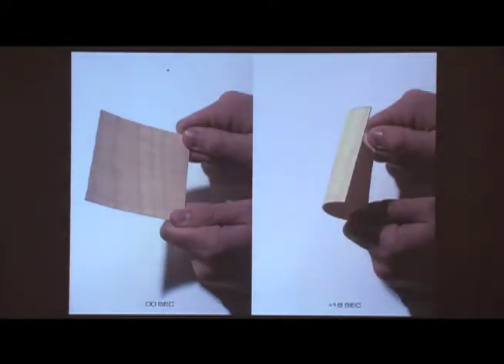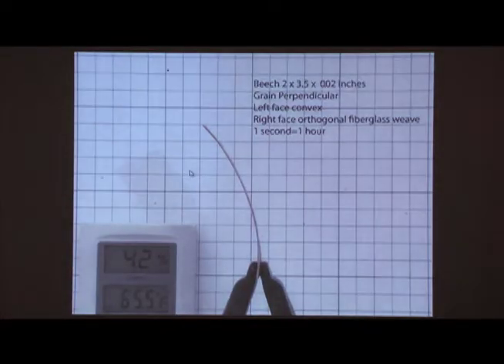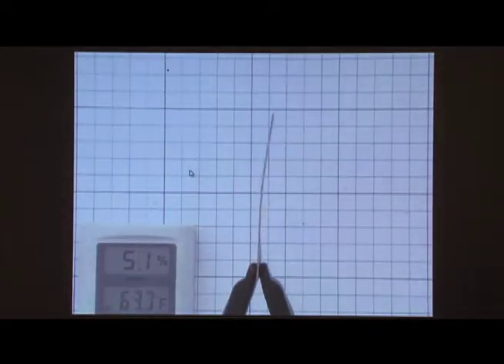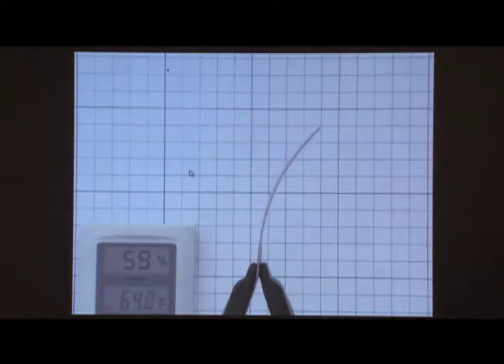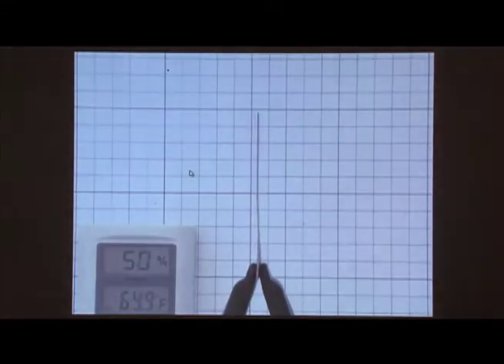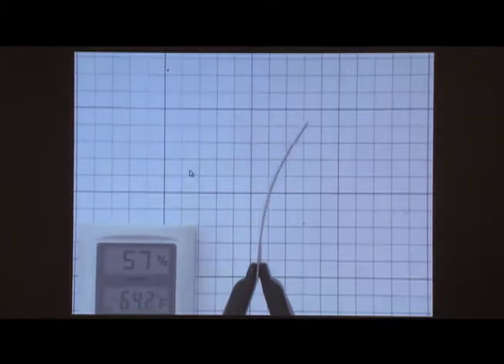So we developed a composite of natural wood veneer and a special composite layer that allows us to mimic this behavior using very cheap wood as a starting point. And here you can see the simple material element. Here you have the changes in relative humidity, and you see an autonomous shape change just by itself. You can program that shape change, so you can make it move this way when humidity increases or make it move the other way. It all depends on the parameters of manufacturing the piece in particular conditions.